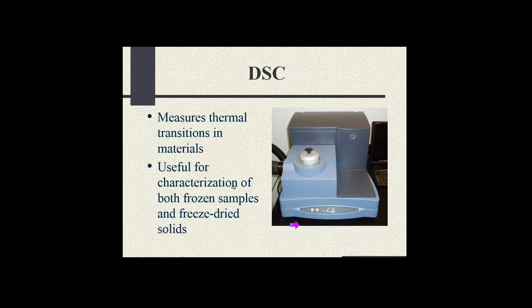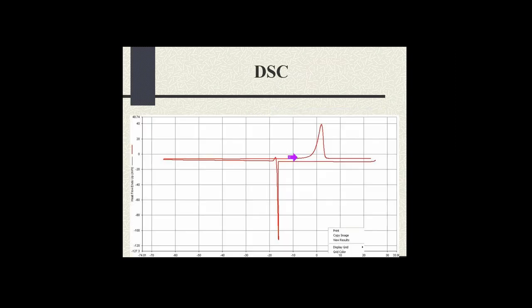We'll skip that. Okay, so here's the system here in our lab. Very simple system. Basically, the lid pops off here. There's a sample furnace and a reference furnace. We cool the samples down, so we start at room temperature. And there's two curves here. One's the warming curve and one's the cooling curve. So we cool the sample down, boom, we see crystallization occur. That's the ice freezing in the sample. We get down to a fixed temperature. In this case, it was about negative 65, and then we warm up and go through our melting events.